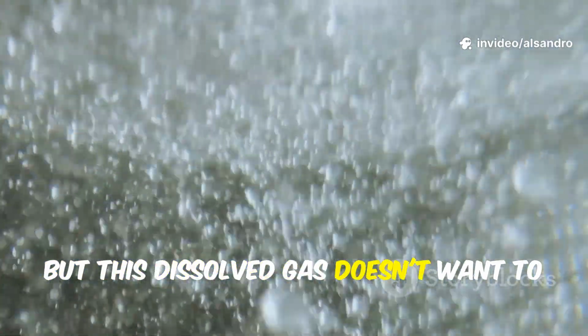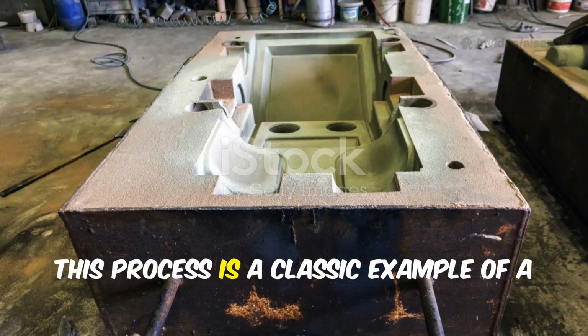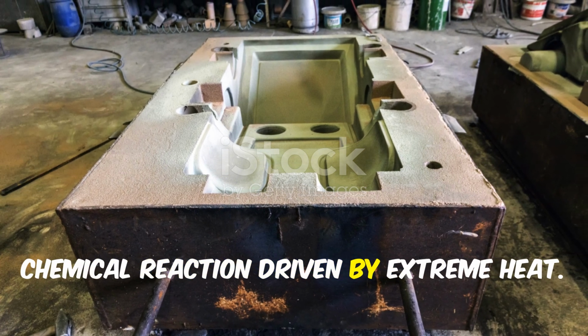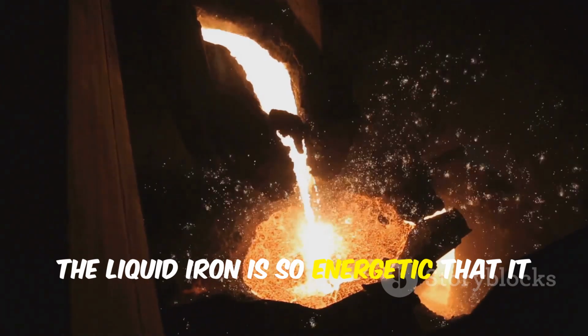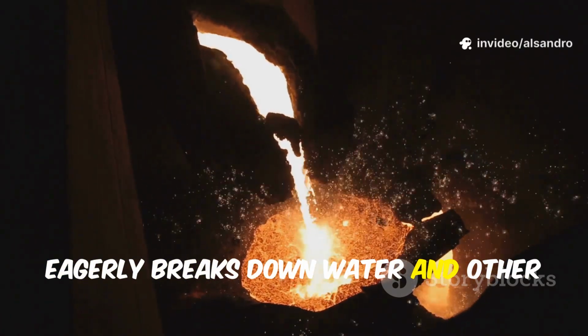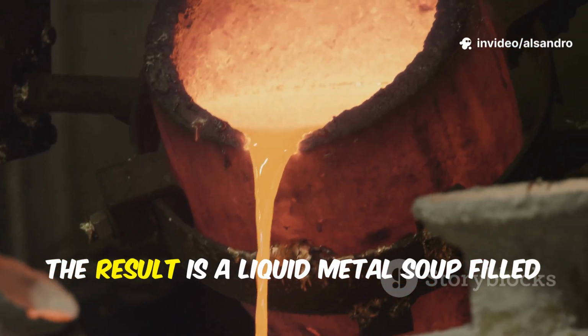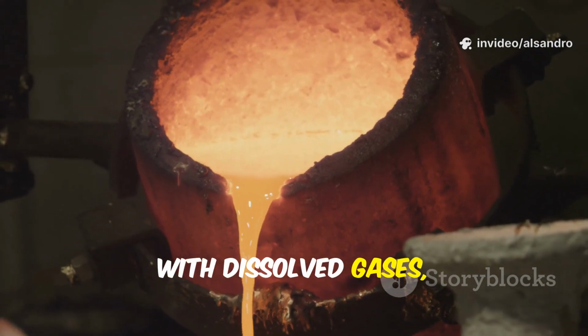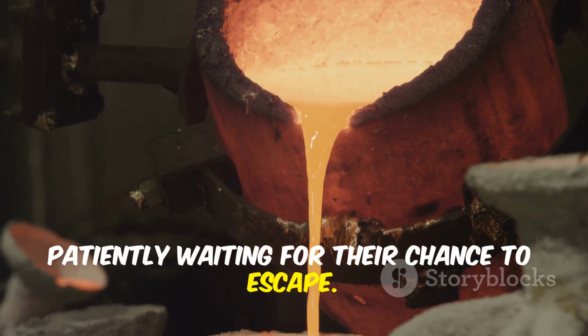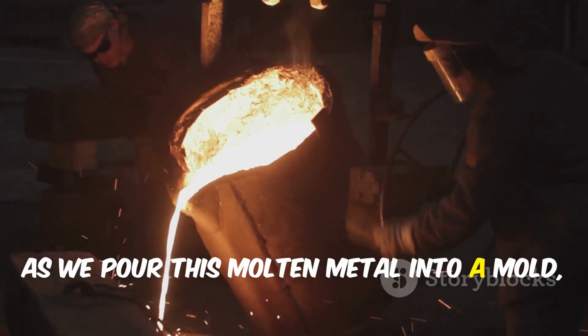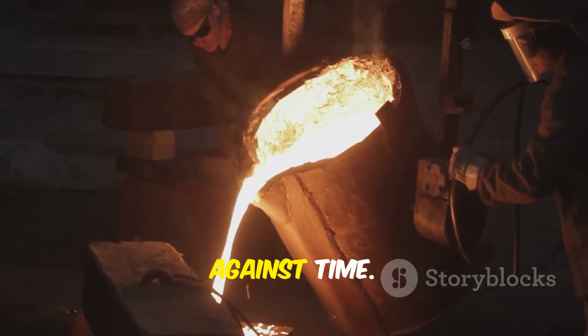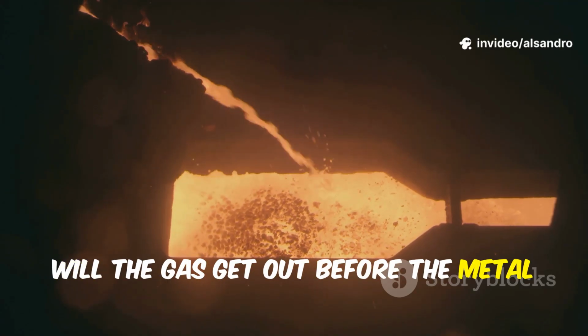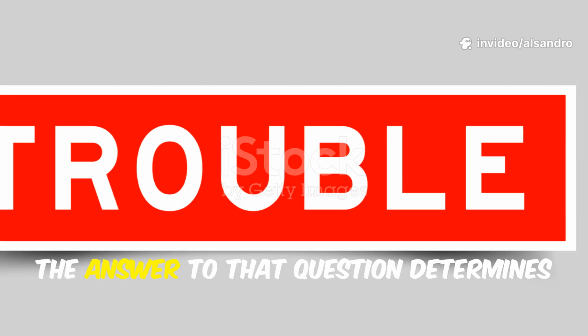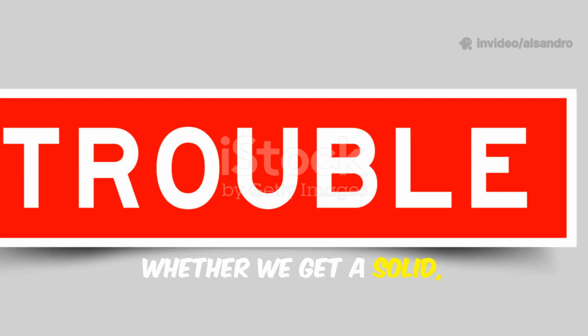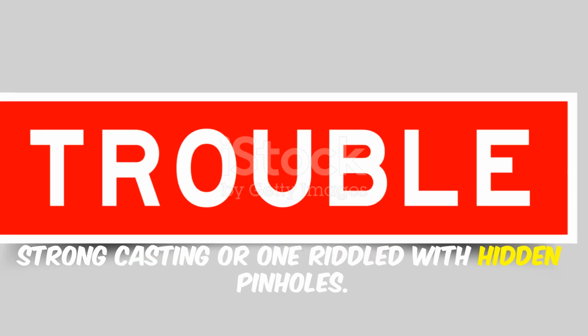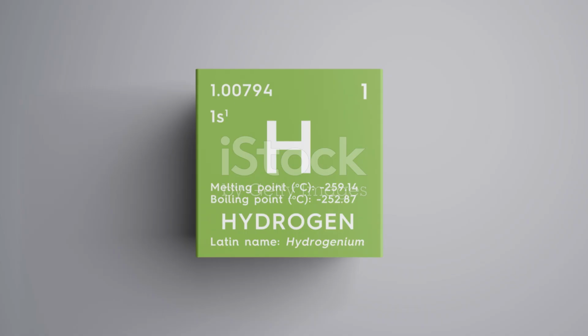But this dissolved gas doesn't want to stay there forever. This process is a classic example of a chemical reaction driven by extreme heat. The liquid iron is so energetic that it eagerly breaks down water and other compounds it touches. The result is a liquid metal soup filled with dissolved gases, patiently waiting for their chance to escape. As we pour this molten metal into a mold, we set the stage for a dramatic race against time. Will the gas get out before the metal solidifies and traps it? The answer to that question determines whether we get a solid, strong casting or one riddled with hidden pinholes. Let's consider this.